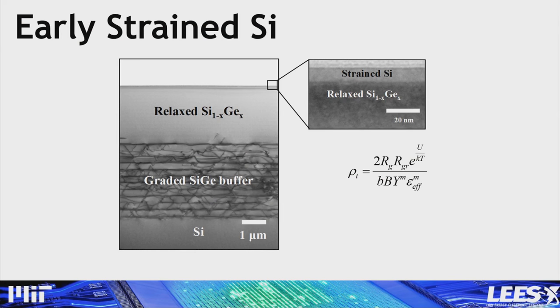And so you can see that because when you stop and grow a uniform layer at the top where there's no more mismatch, at least in this cross-section TEM, you can't see any black lines threading up through the top layer. This image itself told us that, wow, we can build a silicon germanium substrate on top of silicon, and you can't create that any other way.